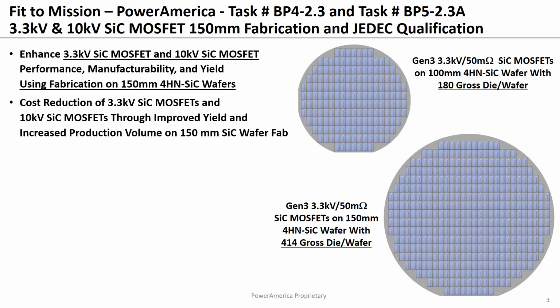facility. To the right here, you see wafer maps of the Gen 3 3.3 kV 50 milliohm silicon carbide MOSFETs on the 100 millimeter silicon carbide wafer and the 150 millimeter silicon carbide wafer. On the 100 millimeter wafer, for these 3.3 kV 50 milliohm silicon carbide MOSFETs, there are 180 gross die printed per wafer. For the 150 millimeter wafer, there are 414 gross die printed per wafer. That corresponds to greater than a 2x increase in the number of gross die printed per wafer for these 3.3 kV 50 milliohm silicon carbide MOSFETs.